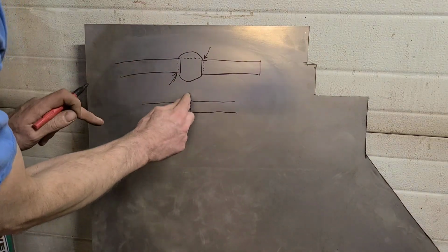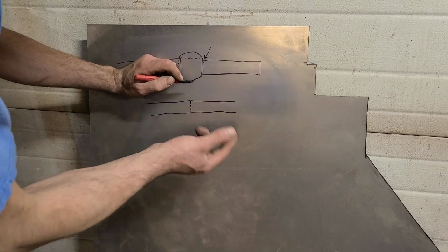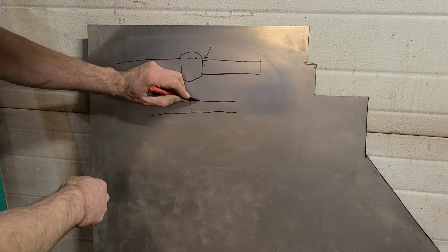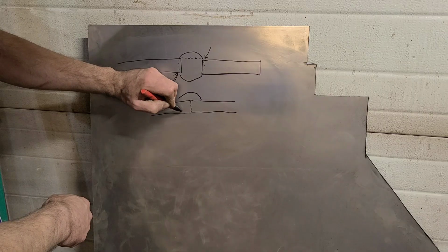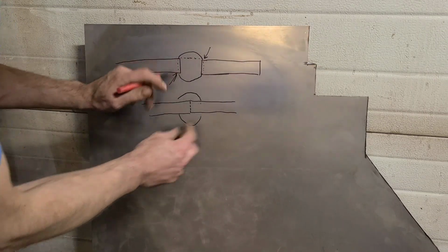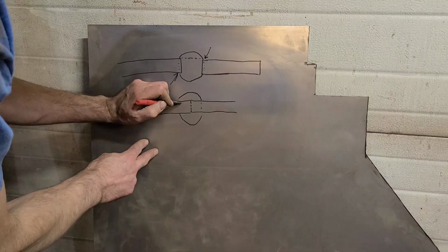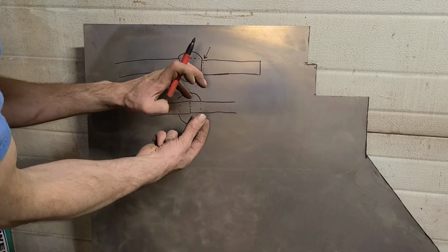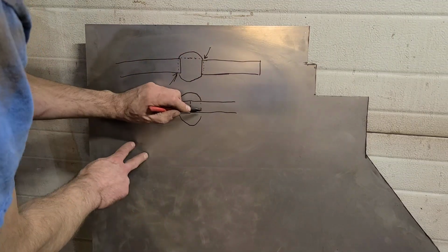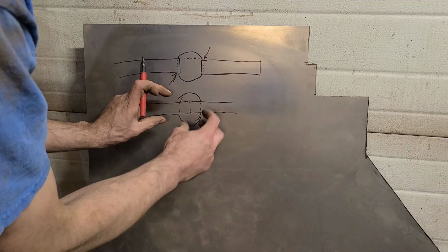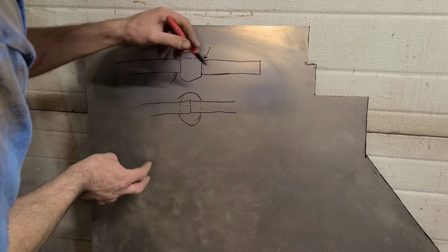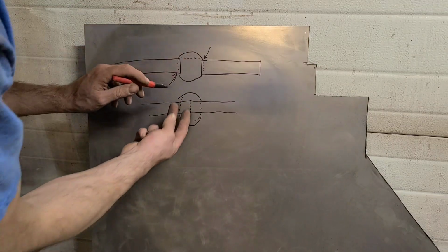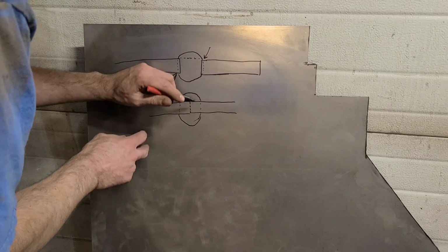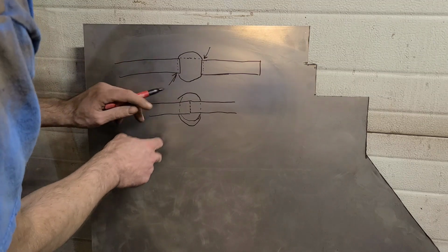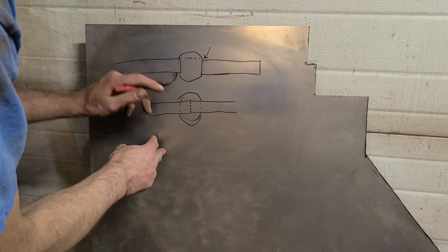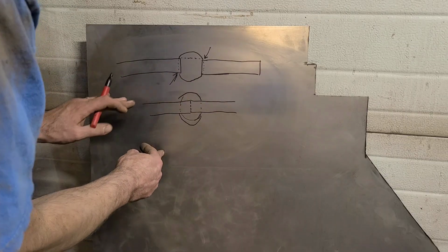Whereas if I have a tight gap here and I have my welder set properly, my technique set properly, then when I go to weld it, it's going to actually, the molten weld is actually going to fuse these two pieces of metal together and intermingle with the actual filler material from the wire feed. And so this is going to be much stronger. Like I said, this is only if it's a full penetration weld. You want to make sure you're getting penetration, obviously, but if we do everything right, then this is going to be much stronger when we go to grind it, and if we have to work it at all.